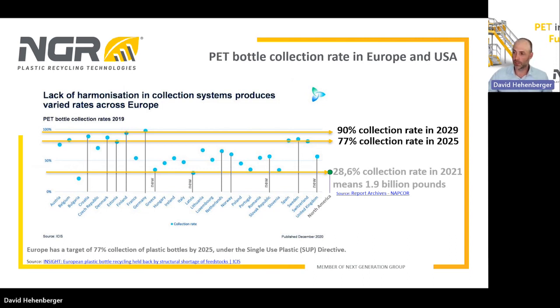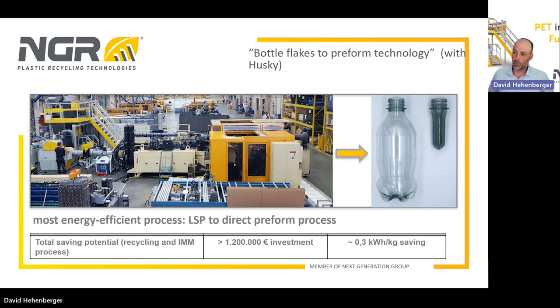If you further want to improve the efficiency of recycling, as I said in the beginning, you can go directly from the LSP reactor to the injection molding process. There is a huge saving potential in investment of more than 1 million euro and also an energy saving of more than 0.3 kilowatt hour per kilogram in total, from the mechanical recycling to the injection molding part.